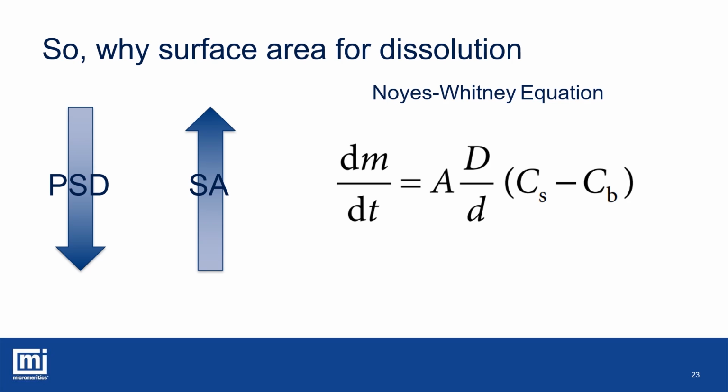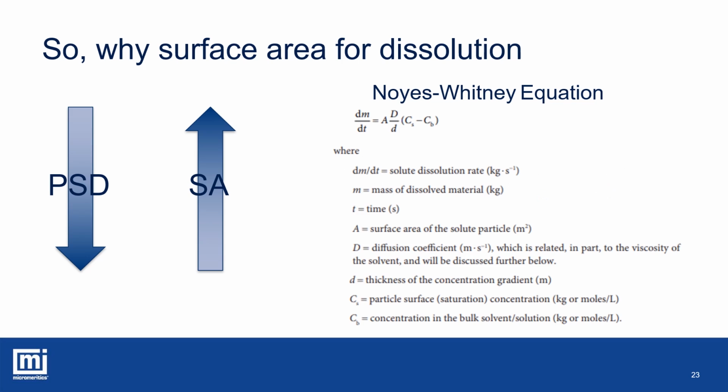So now for a horrible looking equation courtesy of Noyes and Whitney. The Noyes-Whitney equation was one of the first attempts to actually quantify and model dissolution. There have been many refinements since, but all of them are still based on surface area, not PSD. So if we look at the definition of the terms, we can see that surface area is mentioned, but PSD is not.